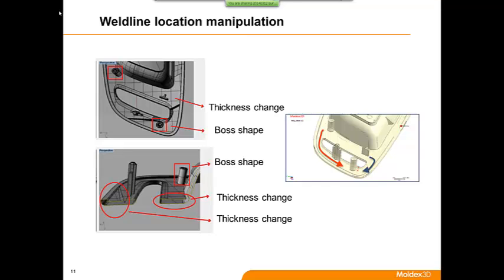And what we're trying to do basically is to change, if you see the right side of the picture, you can see the red line and the black line. There used to be a visible weld line near that location, but through the manipulation of the thickness and the shape of some features, we can change the speed of the red and the black melt front advancement. So by changing that, we can change the weld line location into a less visible place, and maybe by changing the welding angle, we can shorten the weld line as well. So this is something you can also do even if your design has been fixed and there's nothing much you can do about the geometry, but still you can change some of the mold tiny features to erase the weld line.